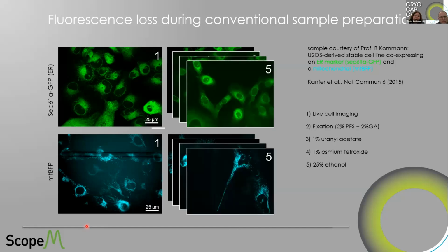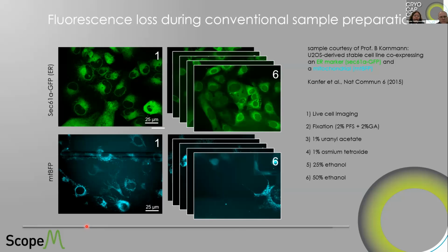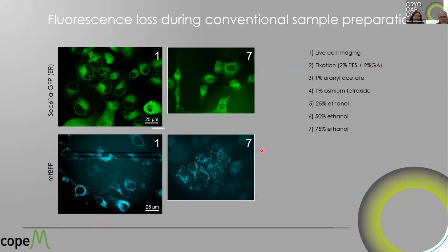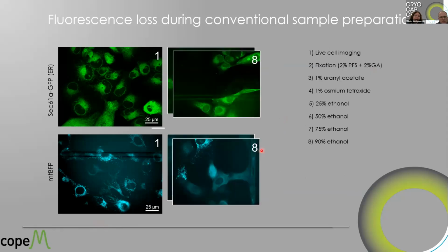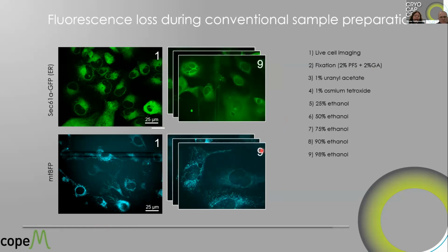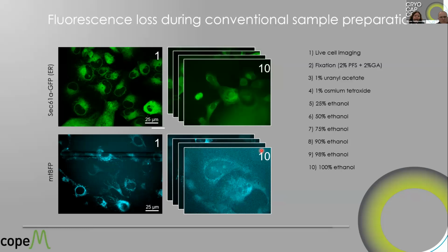Then we start dehydration, 25% ethanol, 50% ethanol. That looks slightly different, but I think this is just an artifact here. The green fluorescence is really still nice. And we're going into 75% ethanol, 90%, 98% ethanol, and 100. And this is where we actually start to lose the fluorescence. So osmium and uranyl acetate did not impair the fluorescence. It was the full dehydration, basically, and this was done at room temperature.